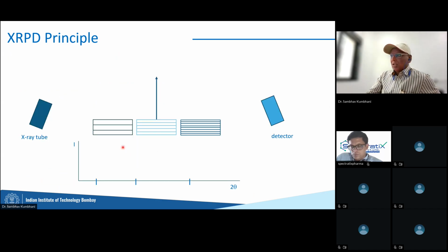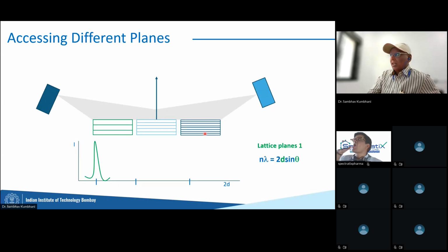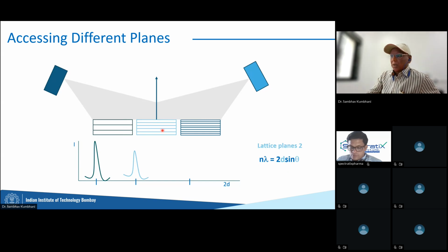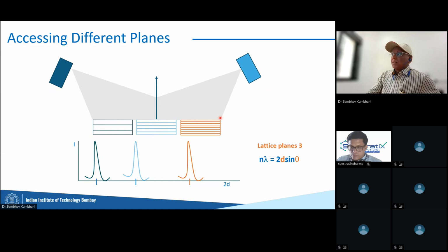This is how we account for that. This is still the same logic. All three of them right now, for example, are completely in a horizontal plane, and their normal is vertically up always. My tube is at the very bottom right now. My detector is also at the very bottom. We turn on our X-ray, we measure our diffraction, but there will be no peak because the angles are wrong. So we move to the right angle. As soon as we move to the right angle, the first peak shows up for this particular type of crystal. Then we move further up, and this is the right angle for the middle crystal. Then we move more up, and we have the right angle for the third crystal. And this is how you generate your X-ray spectrum in real life.